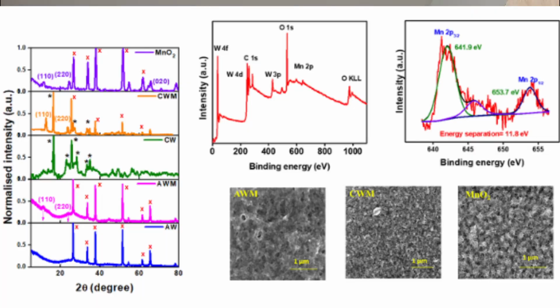The films were then characterized using XRD, SEM-EDS, FTIR, Raman and XPS studies which confirmed the presence of MnO2 on WO3. The charge storage capacities of the electrodes were investigated by cyclic voltammetry. An appreciable rise in the current density values was noted in the films following the application of MnO2 overcoating, demonstrating the improved ability of the active electrode to store charges. Such enhancement can be attributed to the increase in surface area, resulting in more active electrochemical sites.